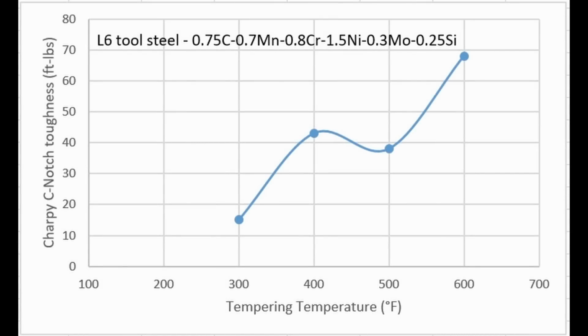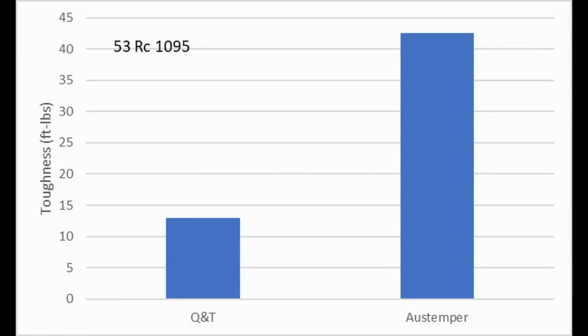Another reason that Bainite can have higher toughness is because of tempered martensite embrittlement. So if you temper martensite in a range of like 500 to 700 degrees Fahrenheit or so, the toughness actually goes down. So the hotter you temper, the more hardness goes down, and usually the higher toughness goes. But in tempered martensite embrittlement, the hardness goes down, but so does the toughness. And so you get worse properties because your hardness is lower and your toughness is lower. And they may have done that to show the bigger difference between quench and tempered martensite and Austempered Bainite for this 1095 chart, which just really shows an extreme example of how much tougher Bainite can be.